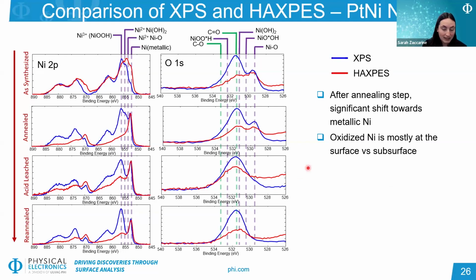So now we can compare this to the HAXPES data, which is probing again up to 30 nanometers, 3 times deeper into the sample surface and subsurface. We start seeing more nickel metal in this red HAXPES spectrum in all of the materials. And we notice especially clearly in the annealed step that there's this significant trend towards almost all nickel metal, with a lot of these oxide species decreasing significantly. And some of those oxides come back after these other treatments, but we still see this really prominent nickel metal peak with the HAXPES data.